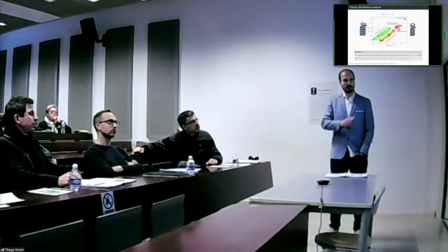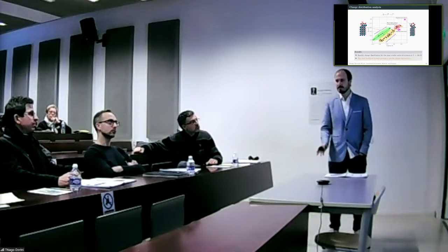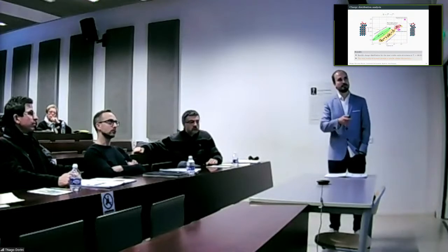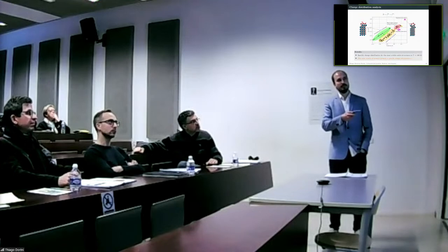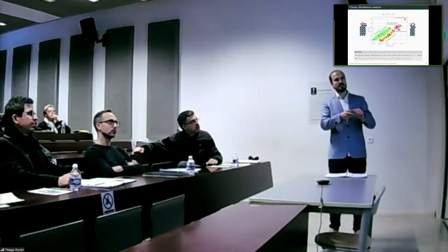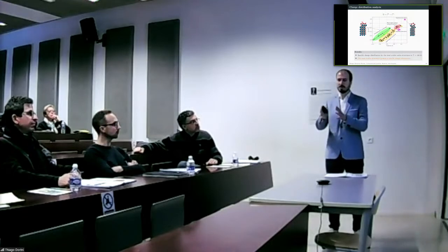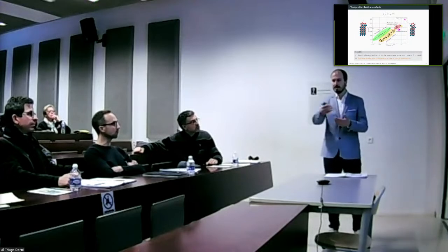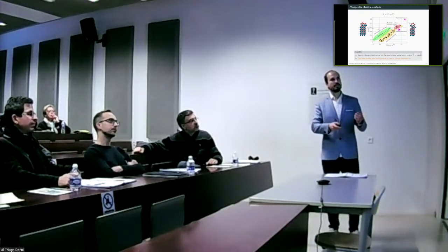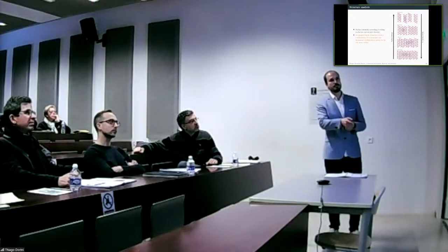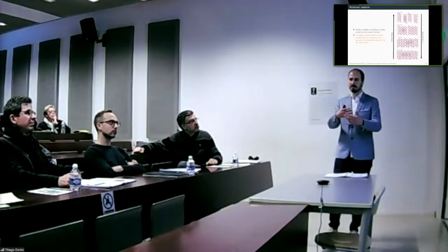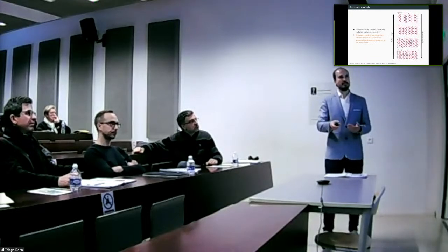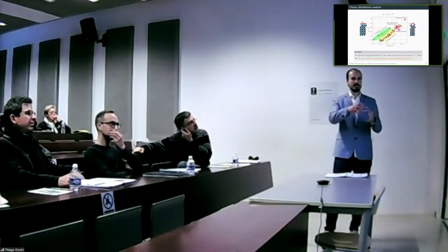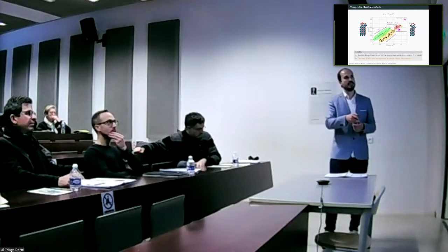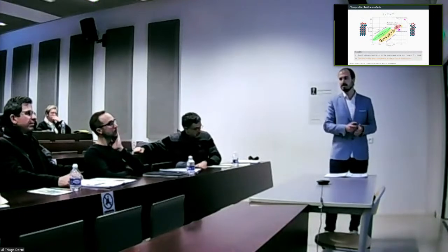I think it depends completely on the composition of oxygen. And we have seen, at least I know that these compositions are really close to the In2O3, so they're rich in oxygen. And also one of the most stable structures, this one, is a bit lower in oxygen. So I believe this also takes into account that when you have much lower content of oxygen, this may lead to the stabilization of these structures.